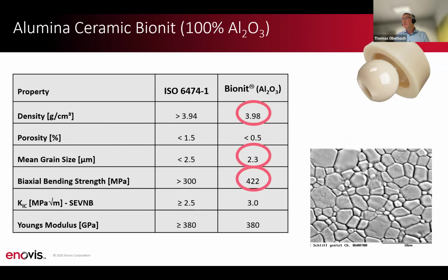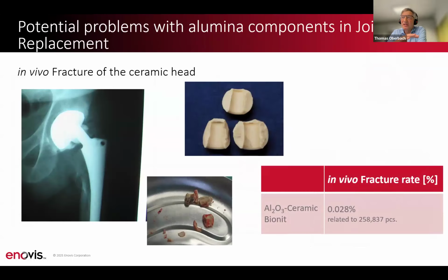But with this ceramic, and this is not the case for our ceramic only, this was the case for all the alumina components when they were used in the hip replacement. In some cases, there was a fracture of the ceramic head in vivo, and I think you can imagine that such a fracture is a worst case for the patient, for the surgeon, who has to revise this, and also for the manufacturer. And our fracture rate for hip heads made of alumina was was 0.028%. That means 28 hip heads of 100,000 implantations fractured.